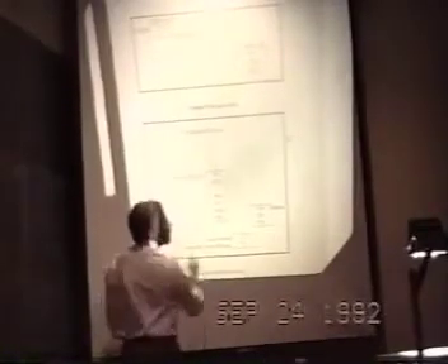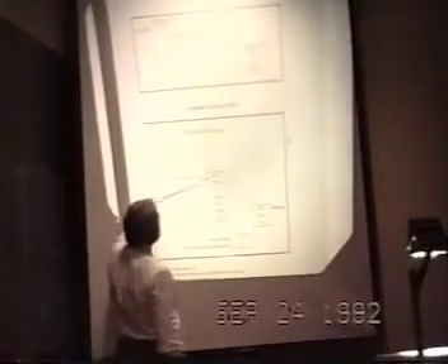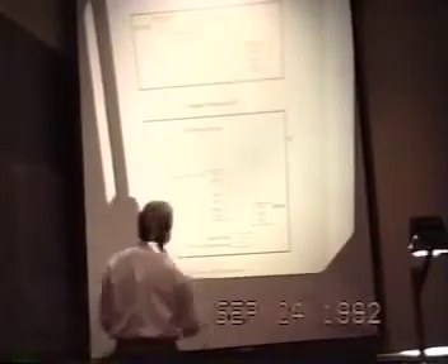P12, I'll briefly describe the results of. It's the first experiment in this series in ambient pressure cells in which we observed excess power. P13 was a light water replicate which went for a similar period of time. No excess power was observed. We then attempted to replicate P12 in a series of experiments, P13, 14, 15, 16, and 17, and observed excess power in each of those experiments, each of them heavy water experiments. P18 was a special experiment and in fact failed within about 80 hours of its operation.